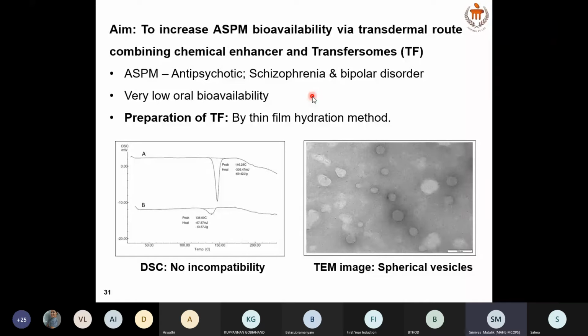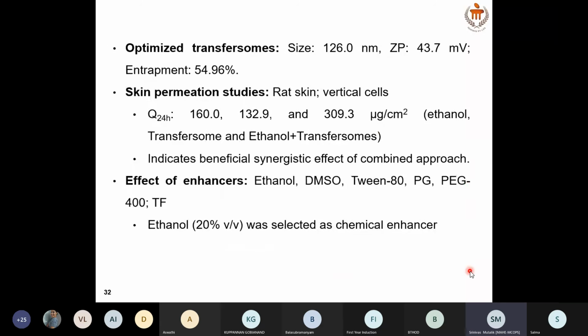First, we prepared the transfersomes by thin film hydration method, and they were characterized with several parameters, where differential scanning calorimetry showed no incompatibility. Then transmission electron microscopic image showed spherical vesicles loaded with drug. Then optimized transfersomes possessed a size of 126 nanometers. Zeta potential was fairly positive, and entrapment efficiency was around 55%. Then we conducted the skin permeation studies using rat skin, using vertical type diffusion cells, and we got the permeation.